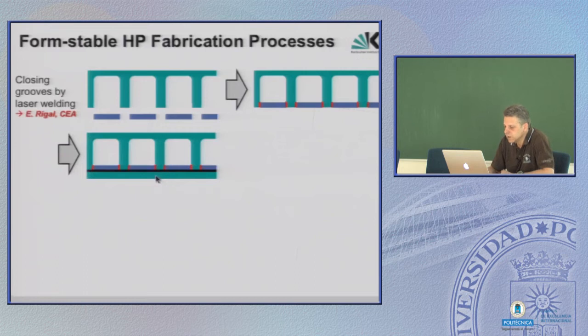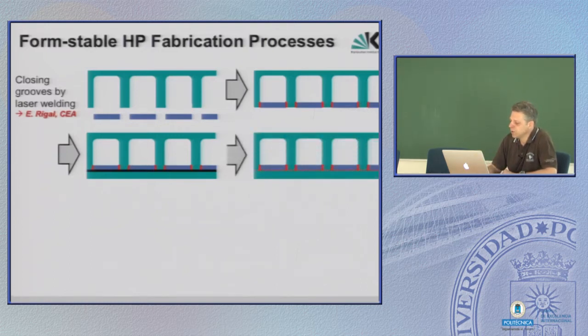This is certainly a feasible idea, but now think about the fabrication of hundreds of first walls, and each of these first walls has, I don't remember, 40 or 50 of these cooling channels, each 3 meters long. So 3 meters times 50 times a few hundred, you end up with several kilometers of these very tiny and delicate laser beam weld lines. And if you have only one tiny leak somewhere in between, you will never find it, and it will certainly destroy the component. So theoretically it's feasible, but risky.